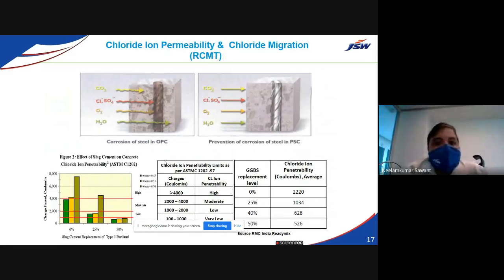If I am casting any concrete with 100% OPC, there will be ingress of carbon dioxide from the environment, and water also, chlorides, sulfates, oxygen and H2O, which will deteriorate your reinforcement steel and corrode it. But whenever I am using GGBS replacement, then chloride penetration and the Coulomb values are mentioned in the table. These are the studies we have done as per ASTM, and definitely you will get good resistance to the ingress of these external enemies, so that they do not deteriorate your reinforcement steel as well as the concrete.